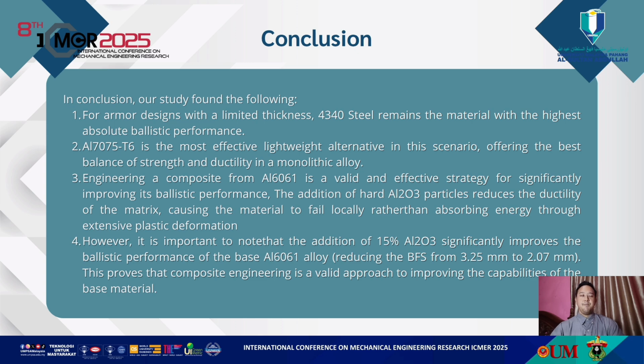The addition of hard aluminum oxide particles reduces the ductility of the matrix, causing the material to fail locally rather than absorbing energy through extensive plastic deformation. However, it is important to note that the addition of 15% aluminum oxide significantly improves the ballistic performance of the base aluminum 6061 alloy, reducing the BFS from 3.25 mm to 2.07 mm. This proves that composite engineering is a valid approach to improving the capabilities of the base material.